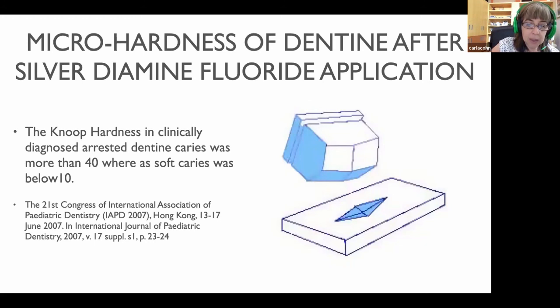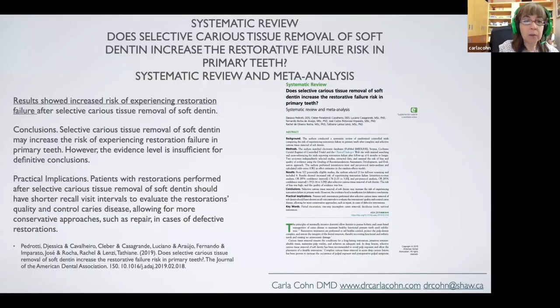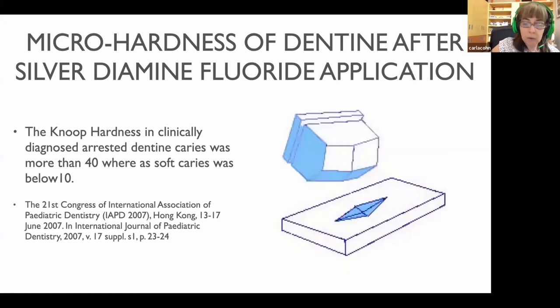I showed you initially when we started talking about incomplete caries removal. I showed you that there were susceptible possibly to failure because of the softness of the dentin. Here we are. And results show increased risk of experiencing restoration failure after selective caries removal of soft dentin. And that when we place the silver diamine fluoride and we increase the hardness of the dentin by placement of the silver diamine fluoride, we no longer have to worry about increased restoration failure because we have increased that hardness of the dentin. Let me show you a silver sandwich.